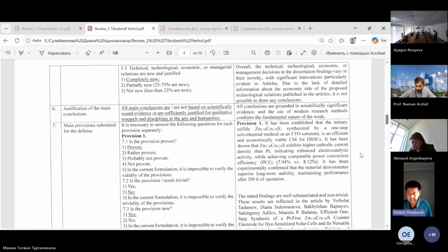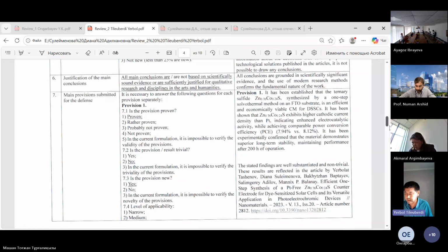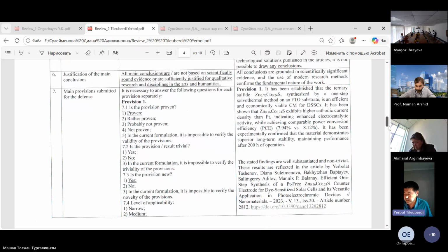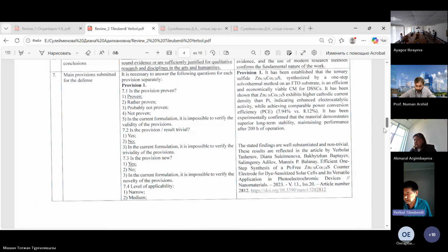The first provision: is the provision proven? It is proven. It has been published that the ternary sulfide, zinc cobalt sulfide, synthesized by a one-step solvothermal method on an FTO substrate, is an efficient and economically viable counter electrode for DSSC. It has been shown that zinc cobalt sulfide exhibits higher cathodic current density than platinum, indicating enhanced electrocatalytic activity while achieving comparable power conversion efficiency.